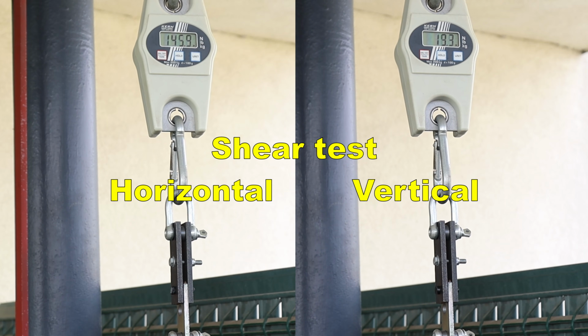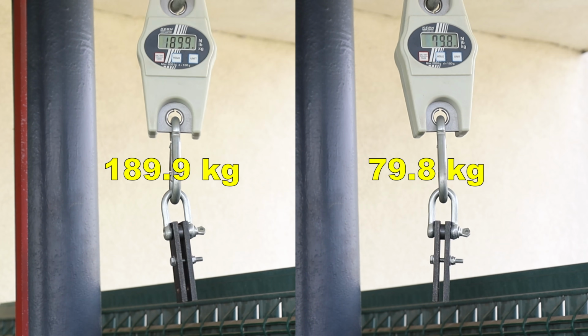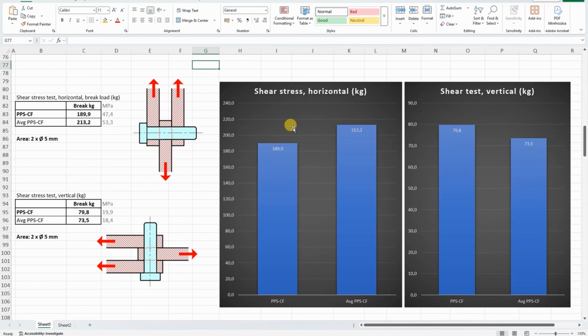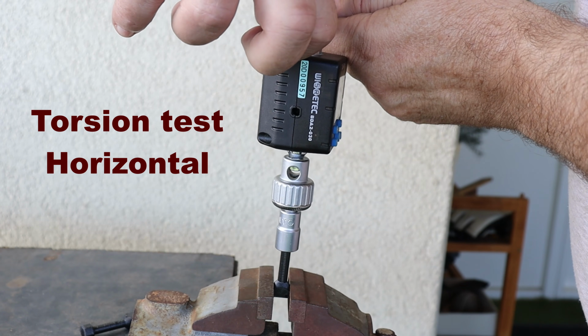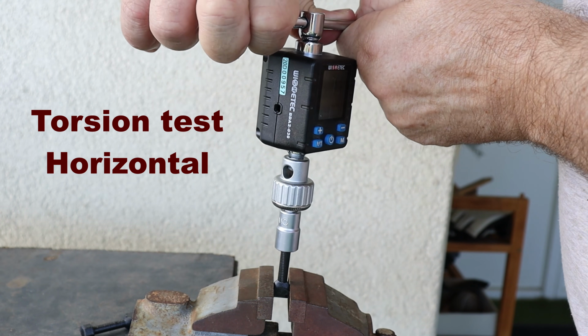Shear test side by side, horizontal and vertical. Printed in horizontal position, a little bit weaker compared to the average PPS-CF. Printed in vertical position, where the layer adhesion is important, a little bit bigger compared to the average PPS-CF, but in both cases this is not a significant difference. Torsion test, horizontally printed.